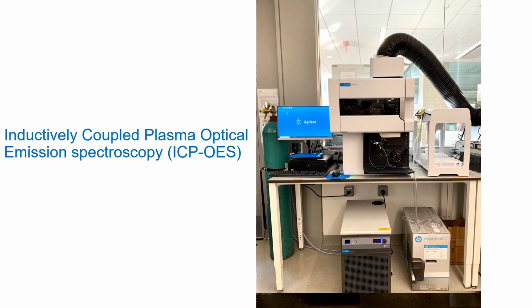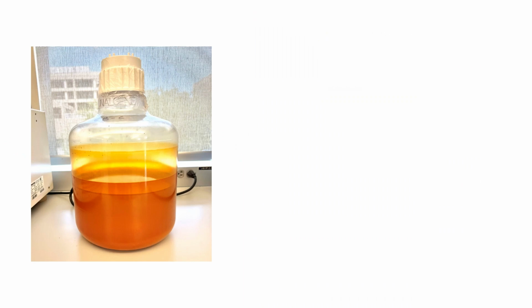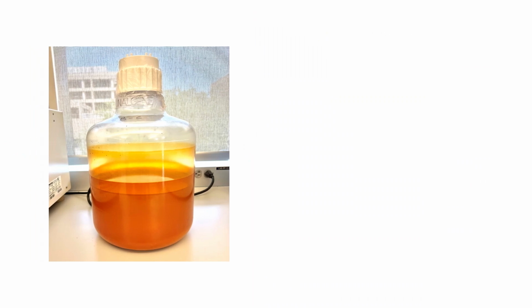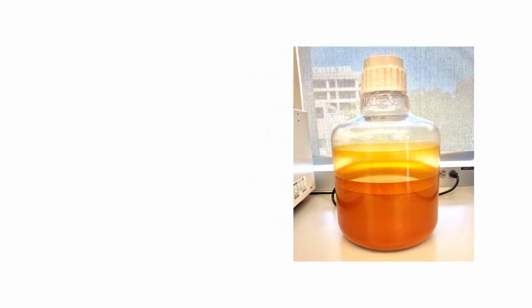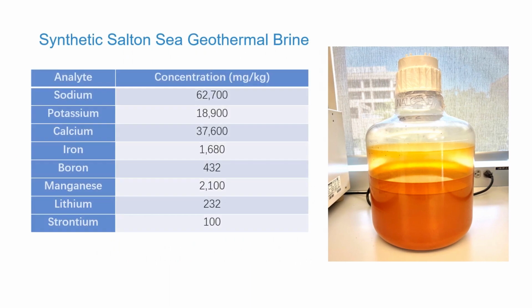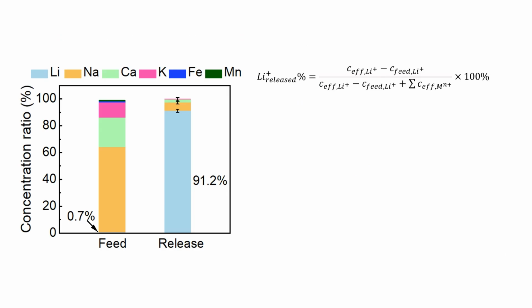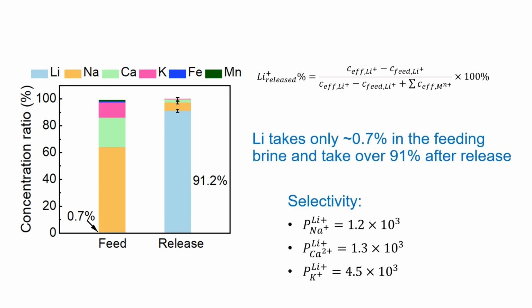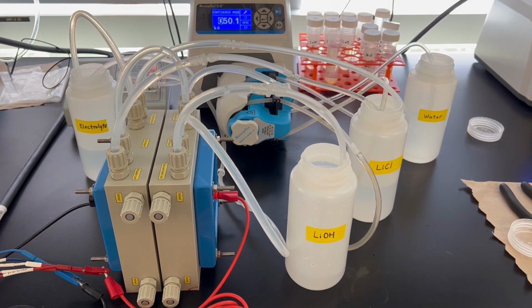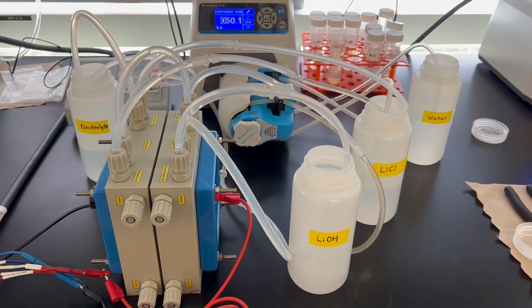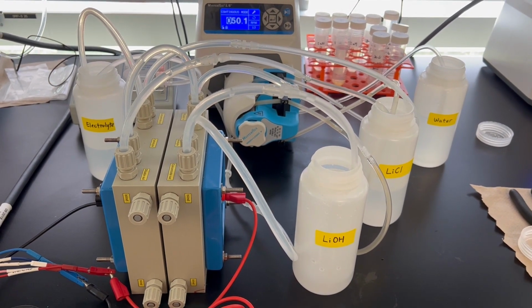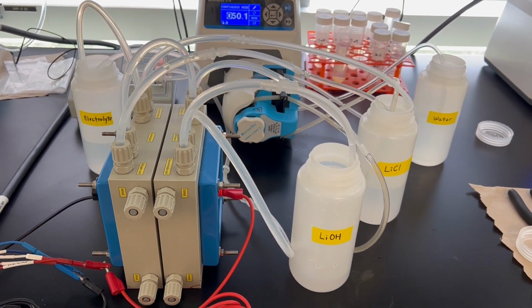emission spectroscopy. By feeding in the complex synthetic geothermal brine containing lithium, sodium, calcium, and potassium, as well as iron, manganese, boron, and strontium, lithium only takes around 0.7% in the influent and takes over 91% in the effluent. The lithium chloride solution was then fed into bipolar membrane electrodialysis cell to produce lithium hydroxide.